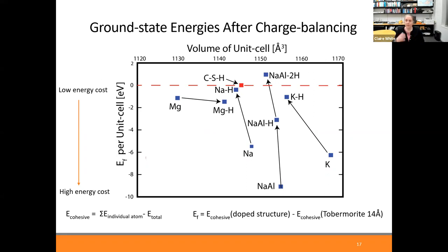And so if we look at the energies of the structures with respect to the original structure, you can see now that if we've essentially charge compensated with the sodium, we're almost as stable as the CSH gel. Likewise, with the sodium and the aluminium, we move even further up on this diagram. So having these hydroxyl units in the vicinity of the sodium and in the vicinity of the aluminium is important in these calculations from a thermodynamic viewpoint. So it's an indication that it could also be important in the real system itself.